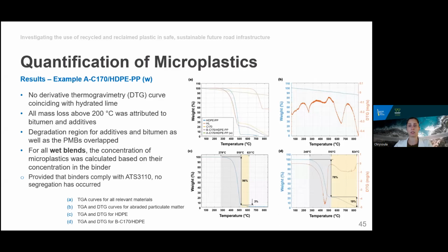The figures in the slide show the results for HDPE modified asphalt by the wet method. But this analysis was undertaken for all particulate matter from all 7 slabs, as well as for the C170 and all 4 binders and all 4 additives. So for this analysis, we assume that the binders used do not segregate, as this is the requirement for national and state specifications. Therefore, even though the degradation regions of the C170 and additives overlapped, we could calculate the concentrations of plastics based on their concentration in the blend.